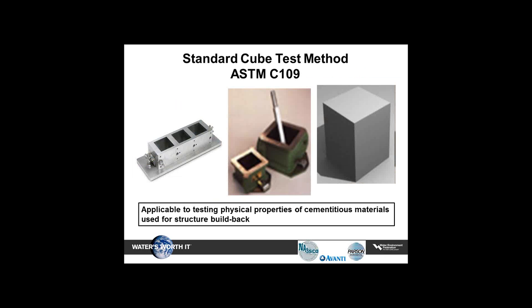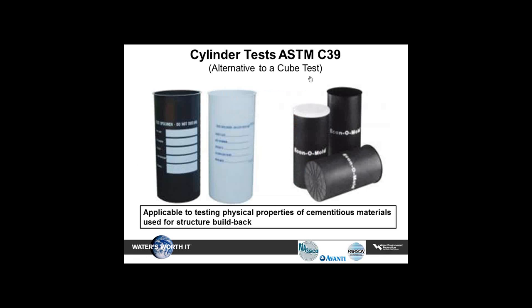Your standard cube testing methods. These are typically methods that are used for cementitious build-back materials, spray-on materials, trowel-on materials, where the material is placed into these small 2x2 cubes. Those are then sent to a laboratory for testing. It is an ASTM C109 recommended standard.